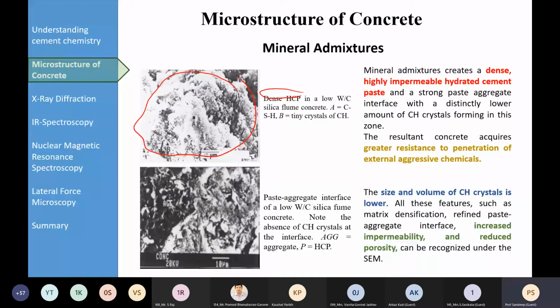So basically it is instilling a confidence that the mineral admixtures are creating a dense, highly impermeable hydrated cement paste and a strong paste aggregate interface with a distinctly lower amount of calcium hydroxide crystals forming in this zone. And due to this, the resultant concrete will acquire greater resistance to the penetration of external aggressive chemicals. And the size and volume of calcium hydroxide crystals will become lower when you add the mineral admixtures. And all these features, such as matrix densification, refined paste aggregate interface, increased impermeability, and reduced porosity, can be recognized under the scanning electron microscope.